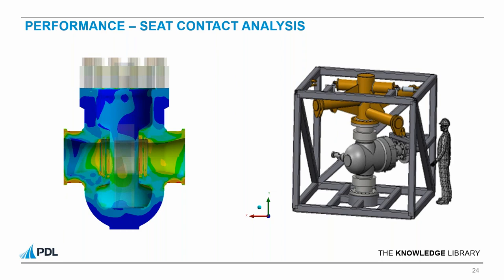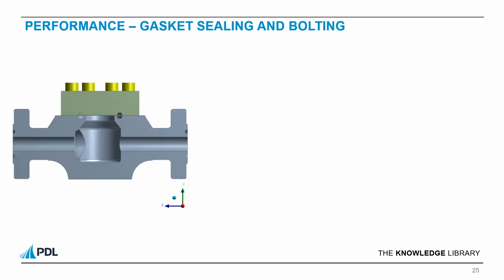The seat seals can also be compromised by excessive seat ring distortion. We would typically extract radial deformation at the seat pockets using a cylindrical coordinate system, and these deflections can then be discussed with the seal manufacturer. Let's now move on to the body and bonnet seal assessment and the submodel that I mentioned earlier. Here we have the swing check valve assembly without its RTJ joint seal because we decided it wouldn't benefit the body assessment under external loading.